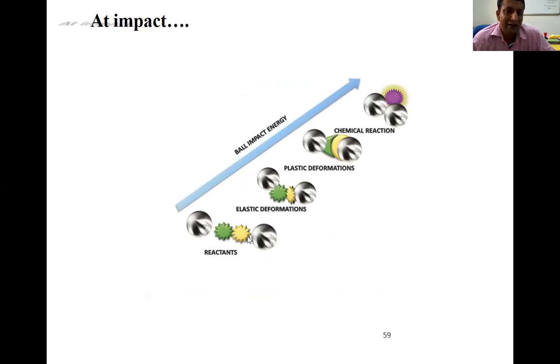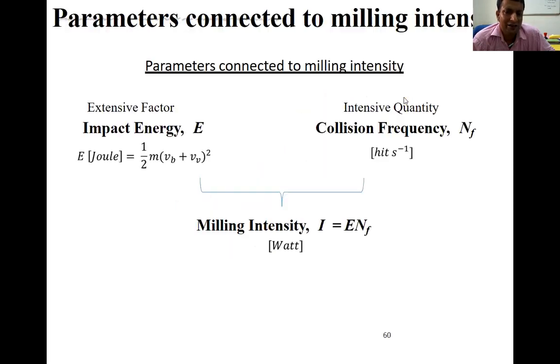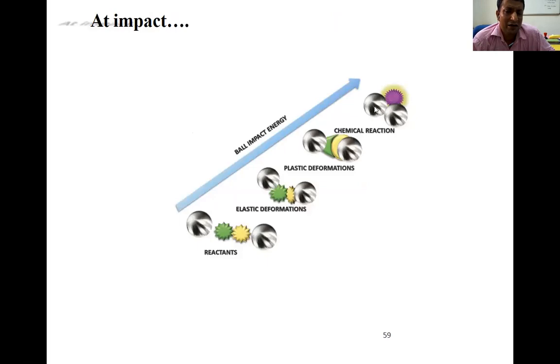So this is what we say, the big advantage of energy ball milling. Directly during the milling stage, the calcination takes place and the particle size is reduced. And of course, there are other parameters to find out the milling intensities, in terms of how much ball energy is imparted to the powders. These are used in high energy ball milling.